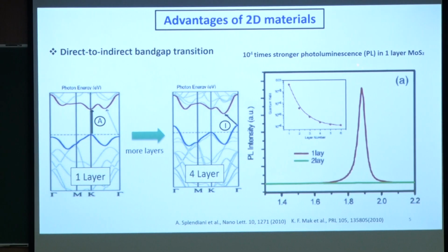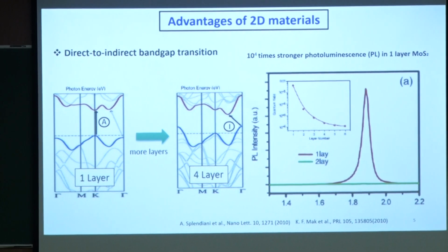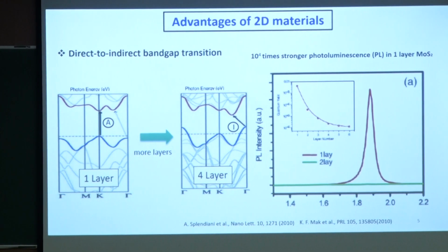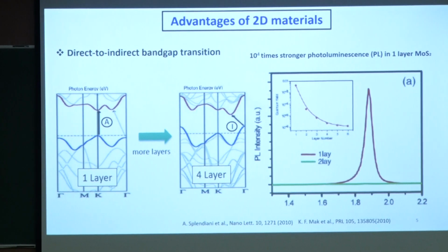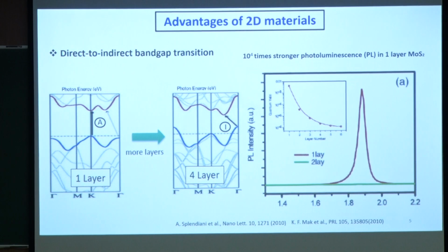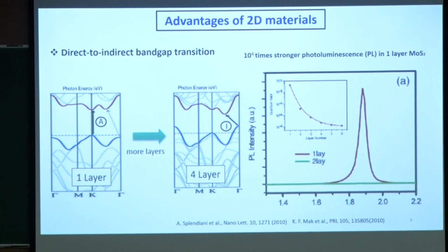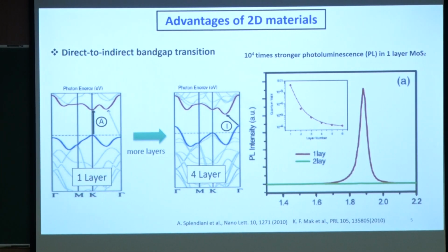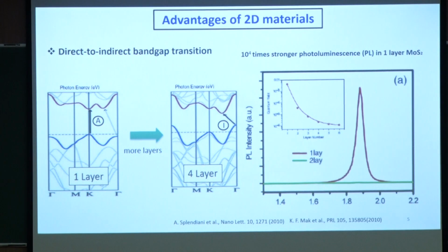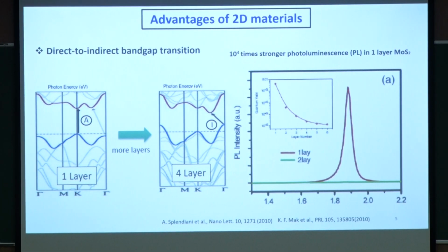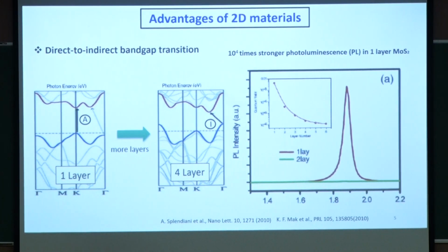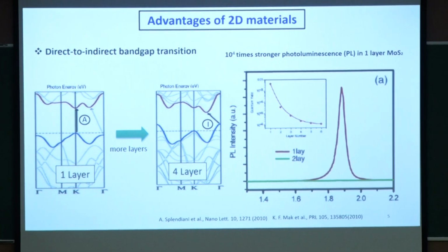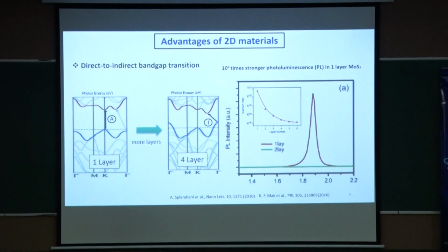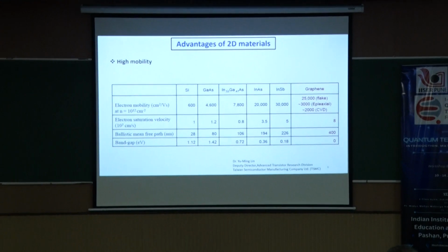The huge consequence is this enhancement of PL. I think 10 to the 4 is the theoretical calculation. Practically, you see 1000 times enhancement, sometimes even less than that. But indeed, the monolayer MoS2 shows a huge enhancement in PL intensity. These days you are familiar with all those things, but just to make it a coherent story, I am going through all these things.